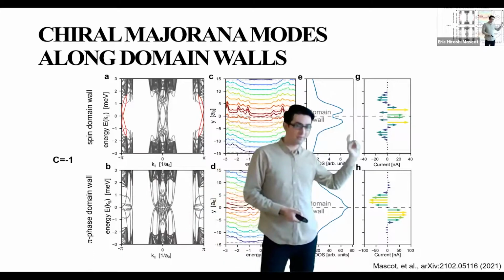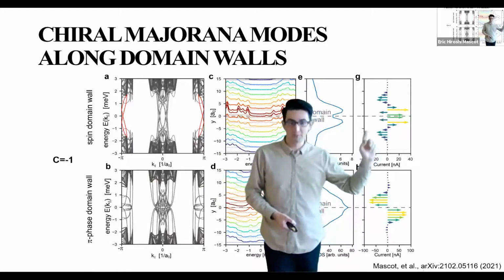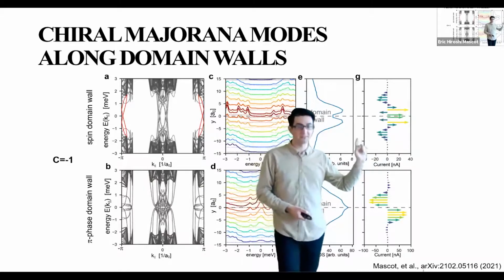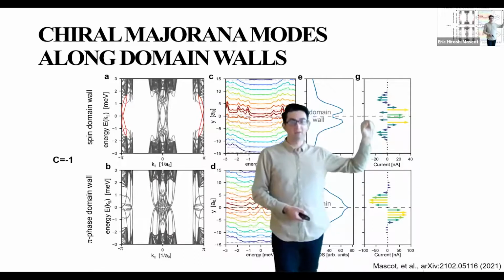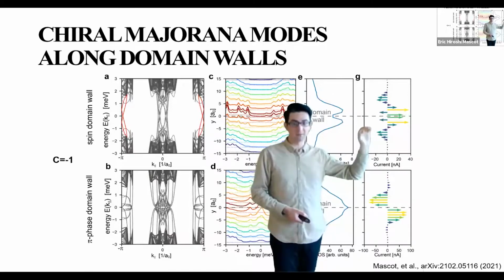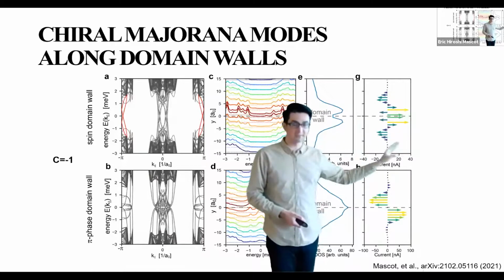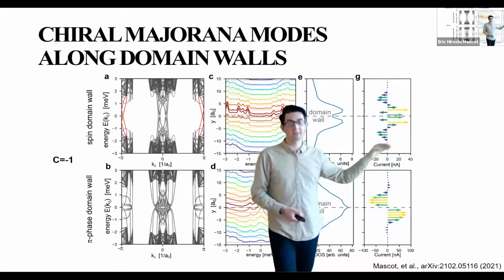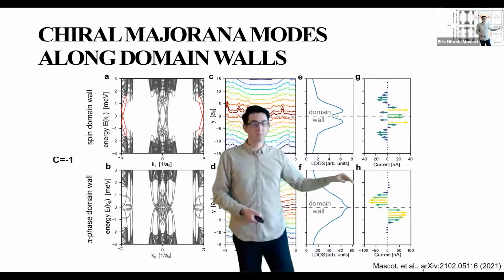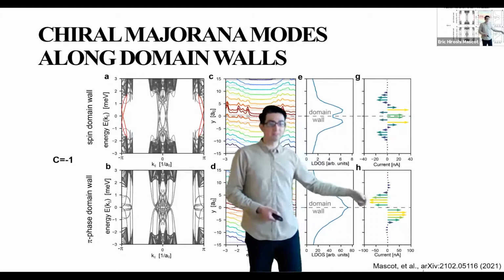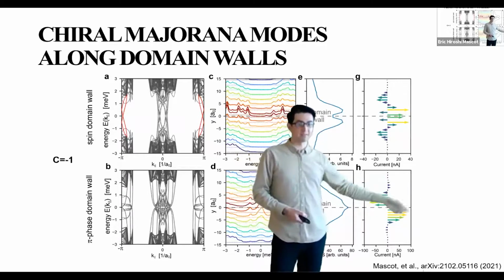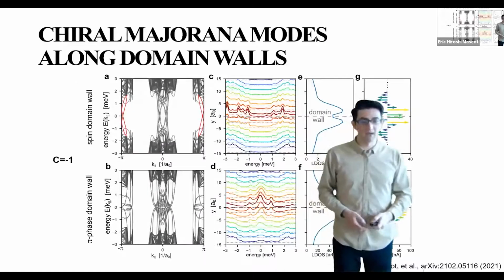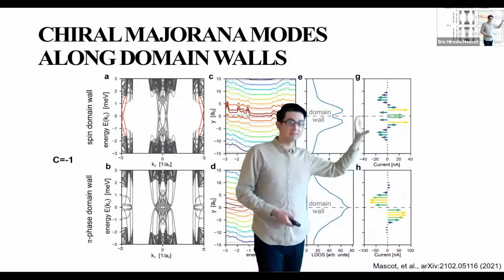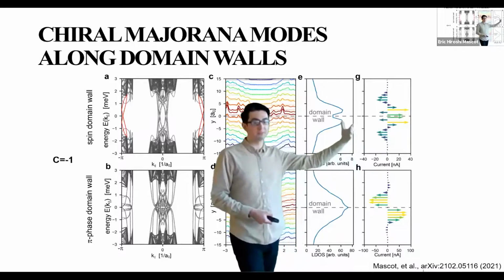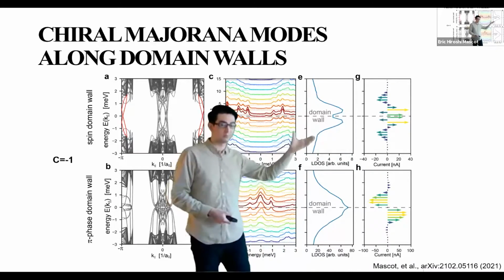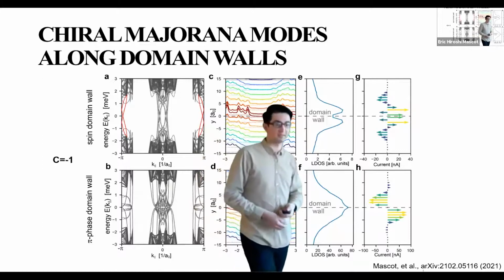However, we can use the sign of the Chern number, which is reflected in the direction of the supercurrent. And on both sides of this domain wall, for a spin domain wall, the supercurrents are facing the same direction. But in the pi phase domain wall, what you get is a supercurrent that is in opposite directions, and the net supercurrent cancels out. So the supercurrent is an additional signature which would be able to discern between a topological edge or domain state and a trivial domain state.